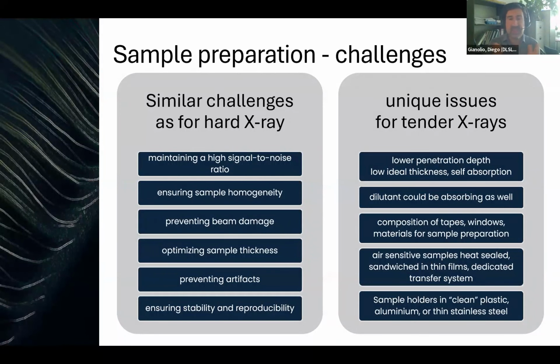Another issue would be to measure air-sensitive samples. While for hard X-rays it's easier to enclose them into a cell or into some packages, here they can be sandwiched, but they should be sandwiched between very thin films, or possibly transferred directly from the glove box where the samples are prepared into the chamber where the sample is measured, with the need of dedicated transfer systems. Another issue could be the sample holder, because as well they could contain some of the elements that you want to measure, or that will have edges in the energy range of interest.